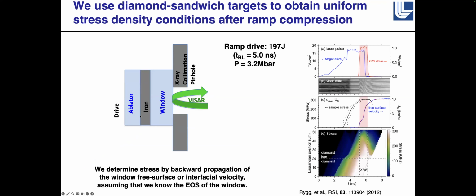So this is more what we did. We used again the helium alpha radiation that was used in Dan Kalantar's, where we have different angles, but we wanted to collimate it now. So we've got monochromatic light, relatively monochromatic light, but it's divergent. And so we collimated it with a high Z pinhole. We put our sample on top of our pinhole.